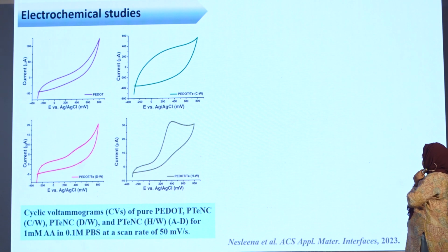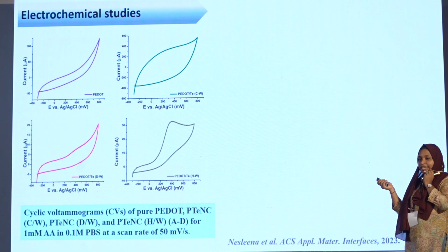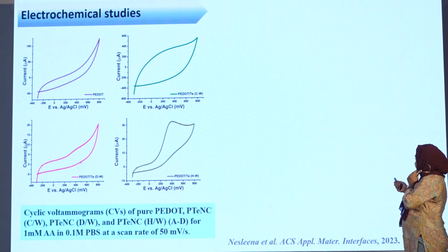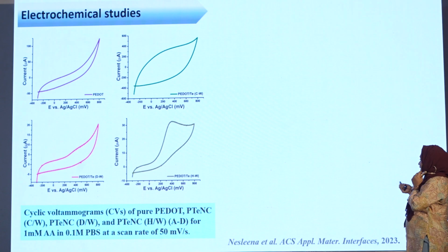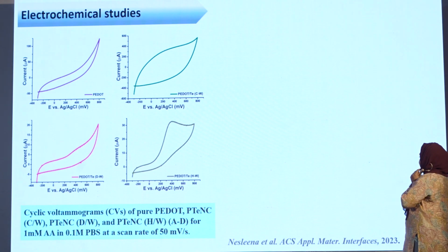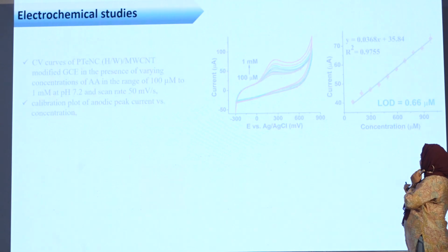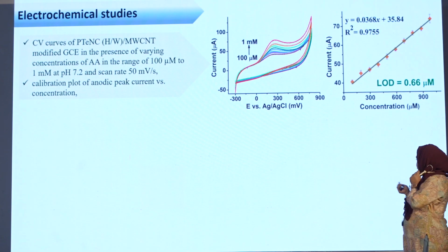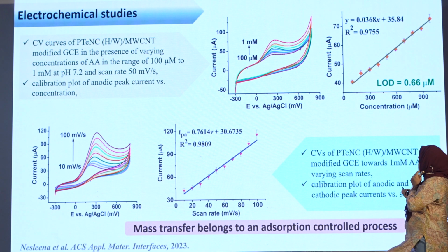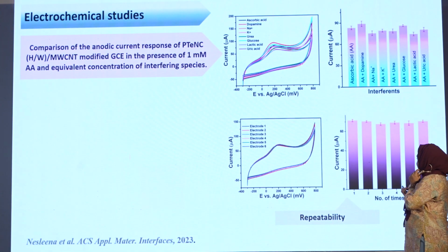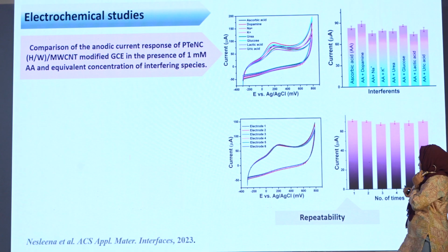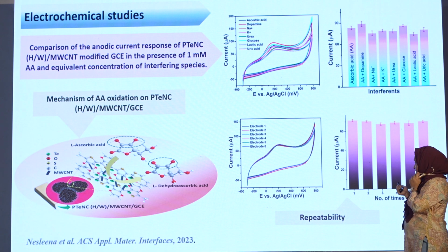We have also analyzed the electrocatalytic behavior, and PTeNC in CW exhibited a capacitive behavior, whereas PTeNC HW showed an oxidation peak for the electrochemical detection of ascorbic acid. Then linear range studies showed an LOD of 0.66 micromolar. The scan rate analysis showed that mass transfer belongs to an adsorption-controlled process. Anti-interference studies and repeatability studies were also done, with the mechanism of AA oxidation on PTeNC also given.